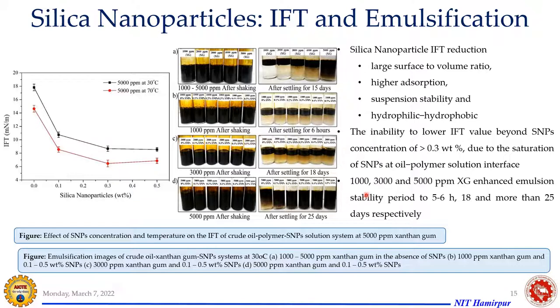And because of such cases, you can see the emulsification is getting stabilized up to a certain concentration when we keep on increasing the nanoparticle concentration. But remember, it also has some disadvantages that we will see. But here you can see the inability to lower the IFT beyond a certain concentration. You can see beyond 0.3, the IFT is more or less the same.